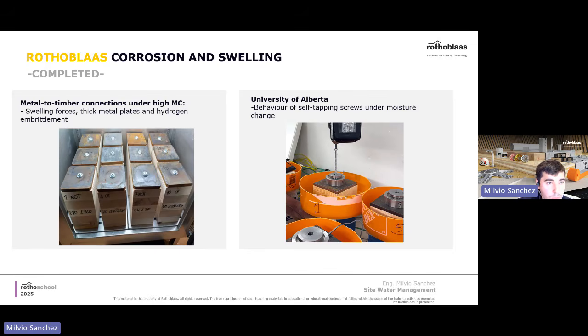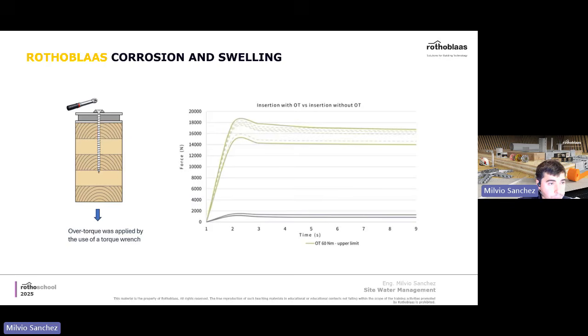And at the University of Alberta as well, we analyzed the behavior of self-tapping screws under moisture content change in glulam beams, placing load cells and evaluating how much force was being transferred due to swelling. One of the interesting results is if you install, for example, a VGS 9 by 200 under a standard 12 Newton meter, which is the installation torque that we recommend for this screw, and if you install it in an over-torque way, like 60 Newton meter, you're going to have different residual tensile force.